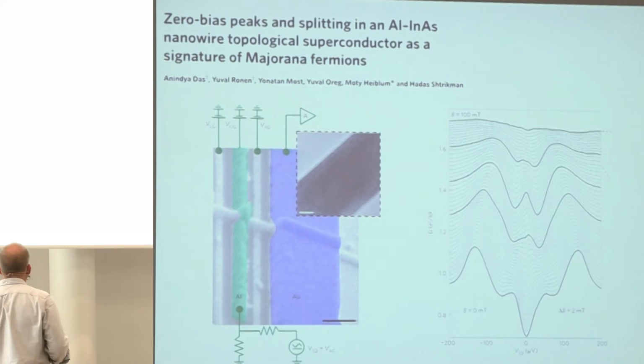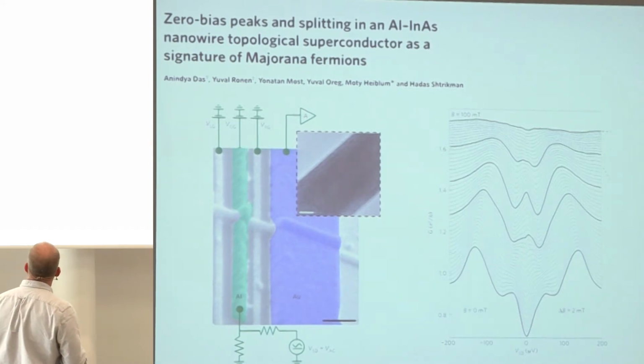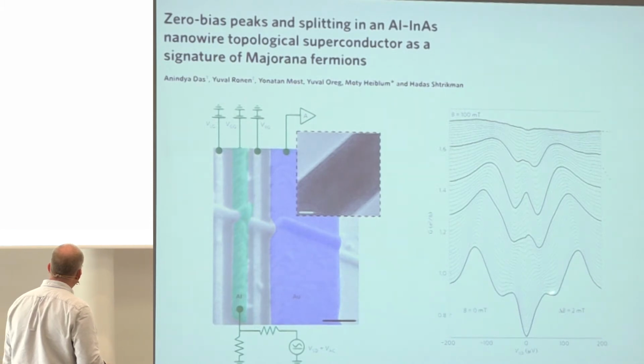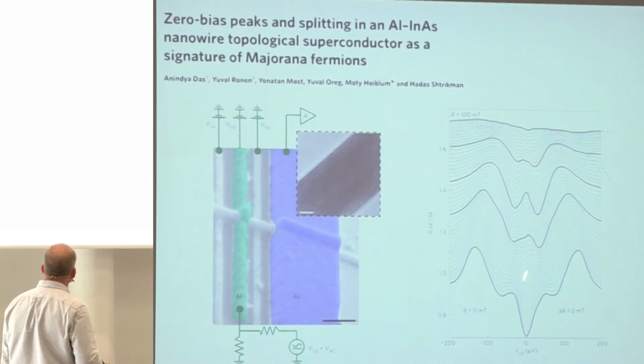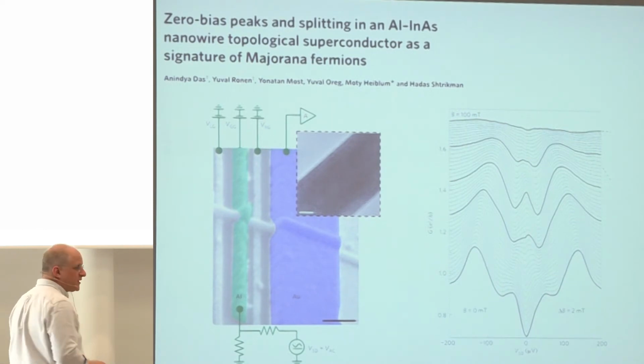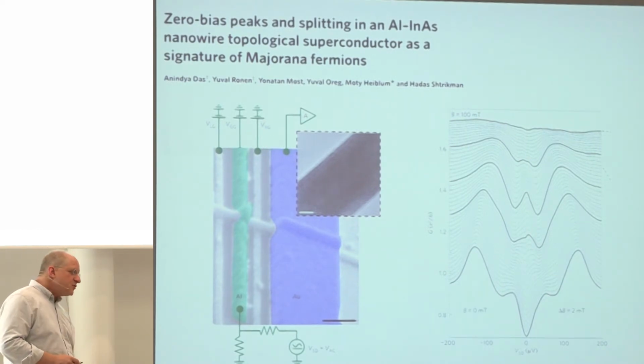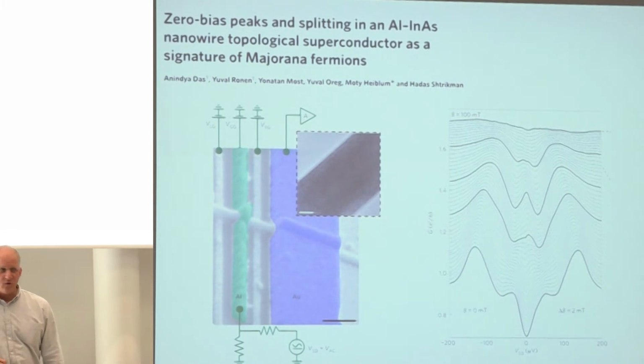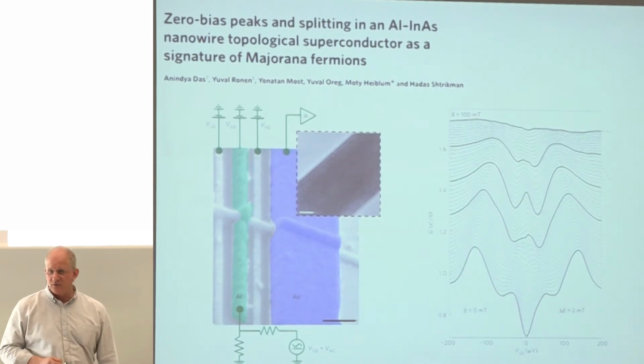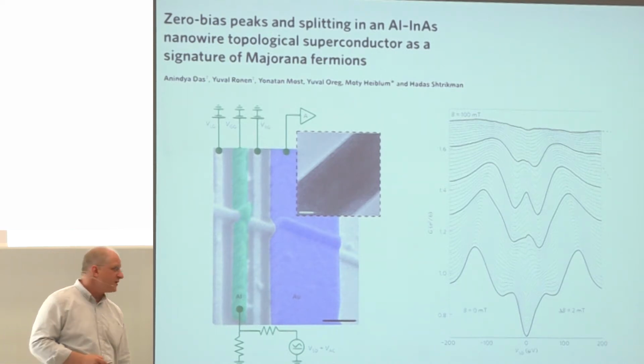That is, here's from the Weizmann group, Moty Heiblum's group, a slightly more complicated density of states, probably one so-called Andreev state below the gap. Here's this edge of the BCS density of states. Turn up the magnetic field, and that dip becomes a peak and then goes away again. The same kind of thing, a very characteristic peak. It's true that you would have liked it to have done a little more of what the theory indicated that it should do, but it was at least surprising that this density of states should appear right out of nowhere.